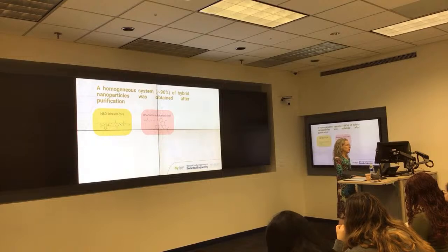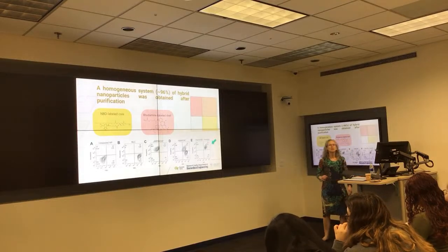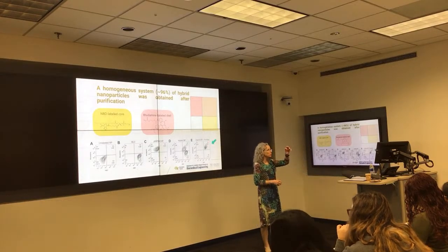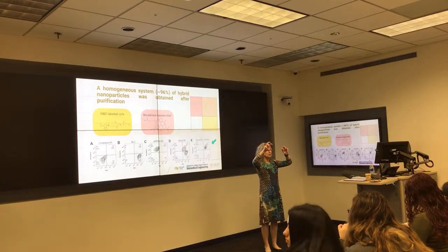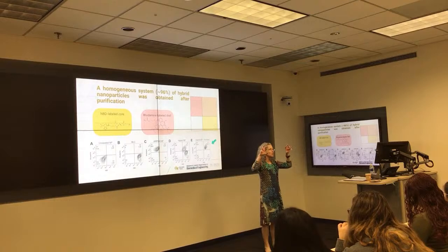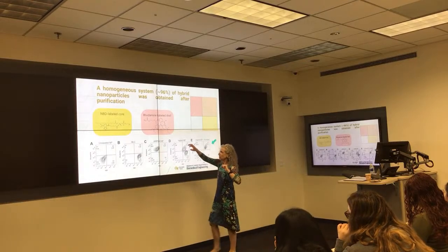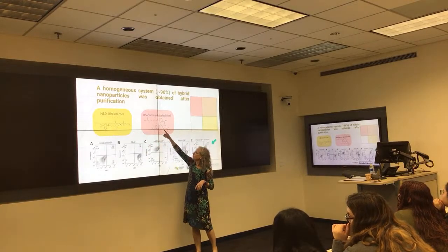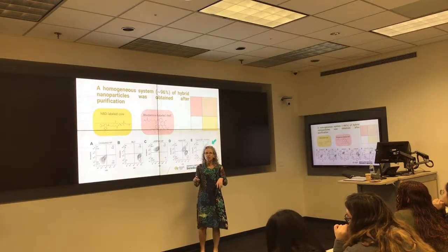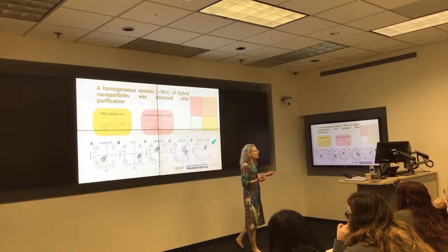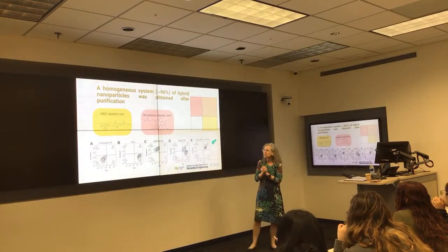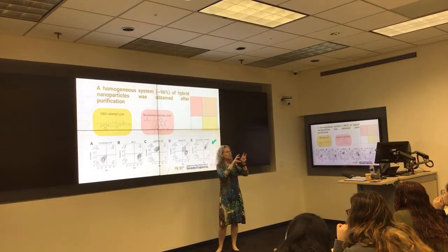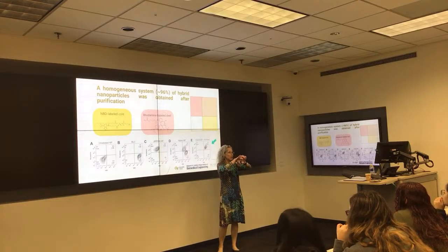Phew. Okay, so then what we wanted to know was, are we really forming a shell around the core, right? Because it's quite possible that we put the cores in and we initiate polymerization and we form NiPAM particles and we have lipid cores and they are completely separate entities. And so we labeled the lipid core yellow and we labeled the NiPAM red by incorporating a monomer into the backbone of the polymer. And we used flow cytometry that you usually use for cells, but you can use for fluorescent nanoparticles. And we said if the shell has formed around the core, we should find overlapping fluorescence, right?